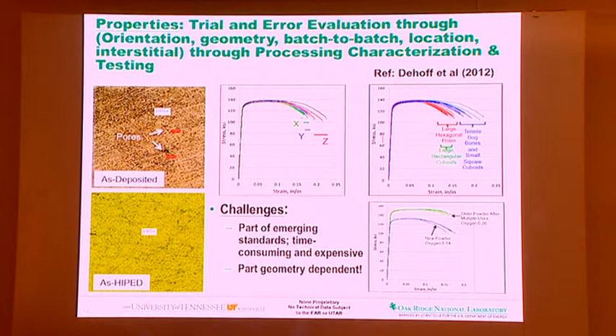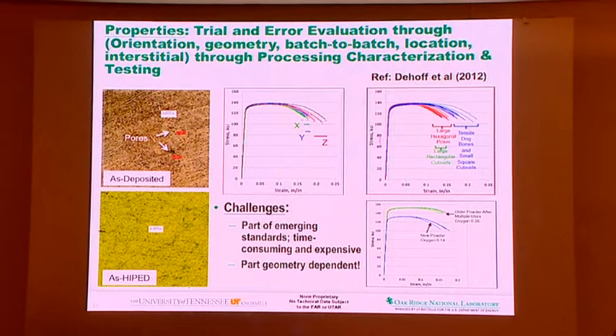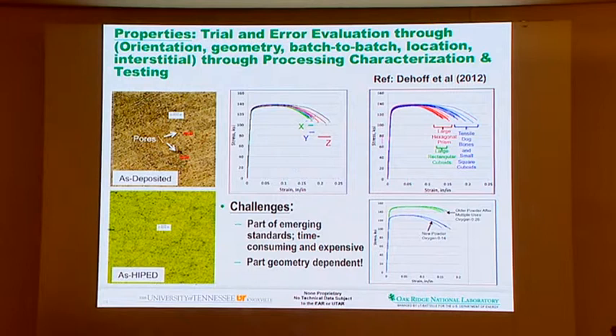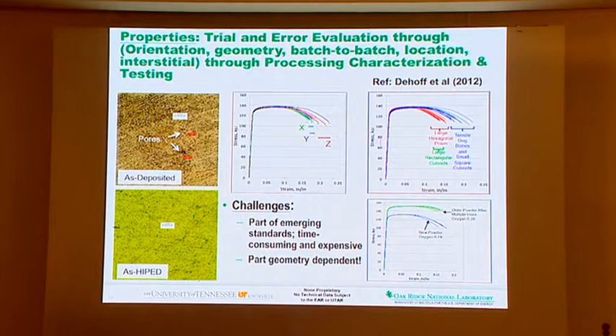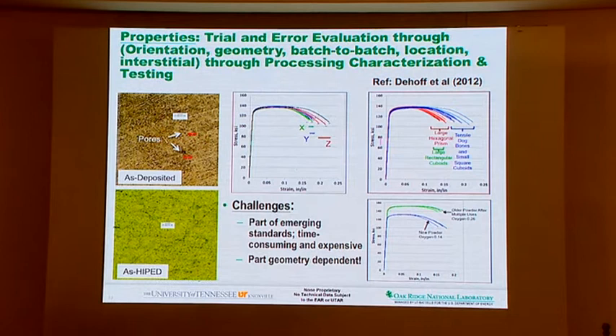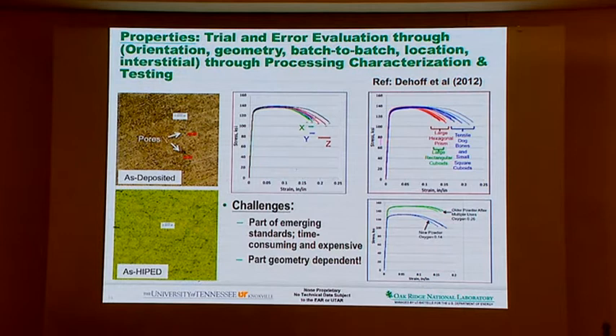Okay, there is one more problem. If you are doing additive manufacturing, you can't throw away the powders, you have to reuse them. In this case, it's a titanium sample. I want you to look at the rightmost graph on the bottom, which is a stress-strain diagram. The blue one is new powder you get from the manufacturer, which you processed. Then you took the same powder and redid the same process, and you will see it gained strength. The reason it gains strength is because it picks up oxygen. If titanium picks up oxygen, it stabilizes alpha, which is an HCP structure, and then you get a little bit more hardening. So you have to remember that every time, your incoming material is changing your composition. It's the same as making chapati. If you leave the dough a little bit, it'll dry out and you can't roll it. In the same way, the material feedstock is degrading as you use it.